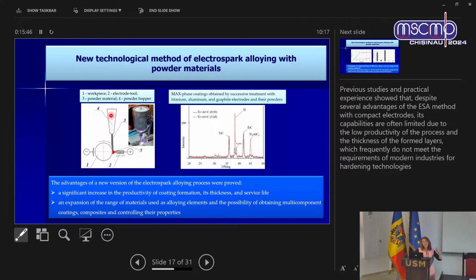Yeah, and this is, I mean, you already can manage to place different non-metallic materials and extend, and for example, to obtain multi-component coatings, composites, and control better properties. And they obtain very strong MAX phase, which contained carbides, of course, again, titanium, which I already mentioned. And it was nice results with a significant increase in productivity because you can increase also the speed of growing the coatings and service life, also the thickness.